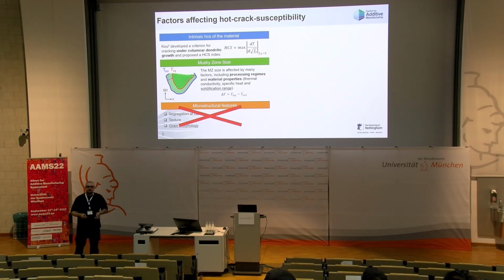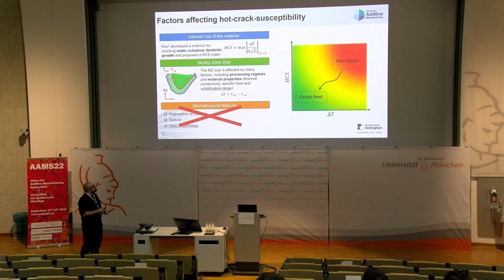So, at the beginning of my PhD, I said, I don't want to do this, I want to investigate something new, so I started on pure columnar microstructure, but trying to avoid hot cracks. So what I thought is that we can do a design map based on these two parameters, just to map the overall crack susceptibility of the material. Usually high-strength aluminum alloys have high HCS and a high solidification range, and we want to be in a region close to the origin of this chart.